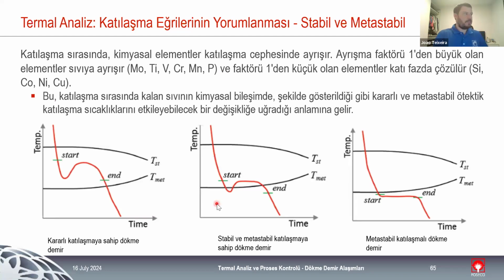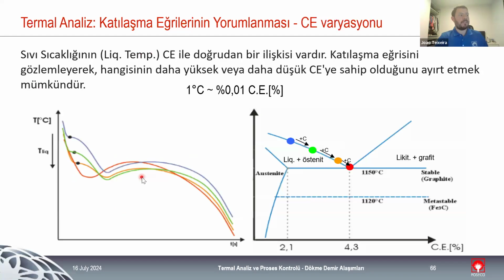And this is just for us to see in more detail the difference between the stable and the metastable temperature. It's between these temperatures that the inoculation step happens and the nodulization step happens. So it's really important for us to control how we achieve both these temperatures in production, and to understand that most of the treatments that we do should happen between these two temperatures. So we need to monitor them, and thermal analysis is really good for this. And we need to control the elements that we are going to add to the melt.